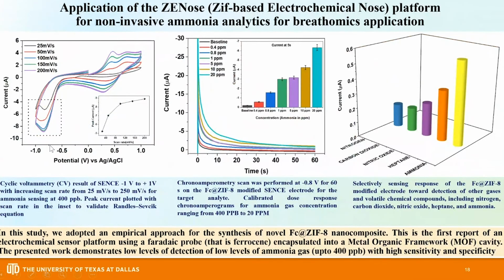So first and foremost we used cyclic voltammetry to see at which potential the target gas is getting reduced. We performed scan rate variation at 400 ppb, and we were able to see the change in reduction curves at this potential, which was further used, that is -0.8 volt, and we used this potential to perform chronoamperometric measurements, and we were able to see a dose-dependent response change from the target analyte gas.